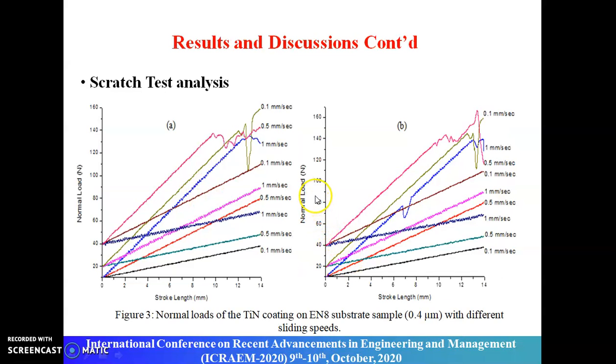In the next slide, figure 3A and figure 3B show the value of normal load increasing along the stroke length. The normal load diagram indicates that there was a decrease in normal load at the end of the stroke length, and this may be due to the adhesive mechanism, which means complete detachment of the coatings from the substrate material.